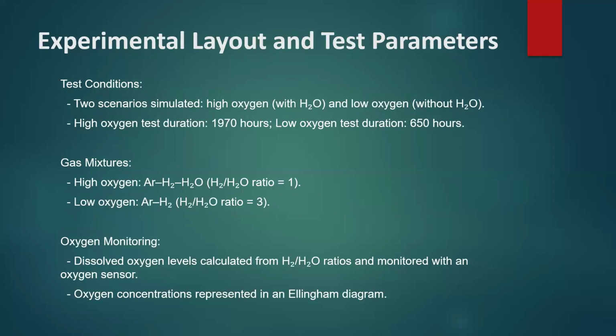For the experimental layout and test parameters, the test conditions were two scenarios simulated with high oxygen (with H2O) and low oxygen (without H2O). High oxygen test duration was 1970 hours, and low oxygen test duration was 650 hours.